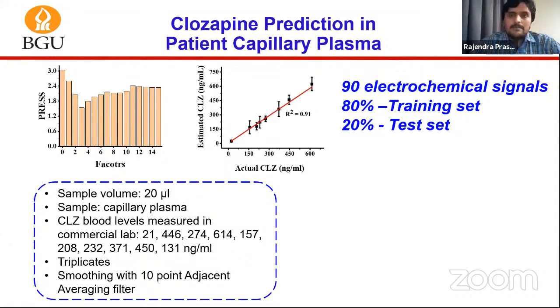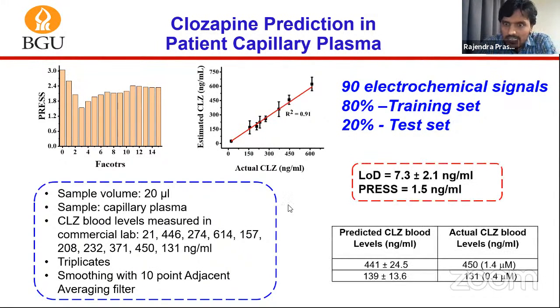So again, we use this PLSR model. For that, we use 80% of the data to train the model, to build this PLSR model, and then 20% of the data to predict the model performance. Here again, 3 latent variables give you the minimum error value for the PRESS, and they can represent the maximum variance of the total electrochemical data set. The PRESS value is calculated as 1.5 nanogram per milliliter, and the limit of detection is 7.3 plus minus 2.1 nanogram per milliliter, which is very low and a very good performance using this multi-electrode array setup.